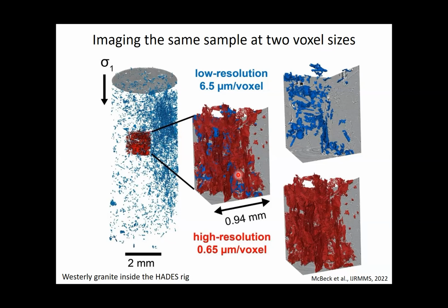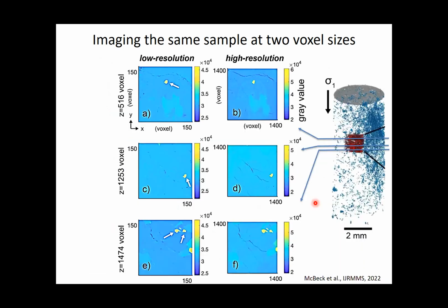So the red image is the porosity at a resolution 10 times higher than the whole sample. So we can zoom in the sample and extract more pores. And one thing you can start to see is that the red image, the sample image at higher resolution, is different from the blue image, just because at higher resolution we can image thinner fractures that do not show at low resolution. So we have these two images. Now we can start to compare them.